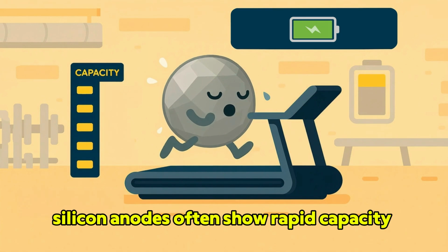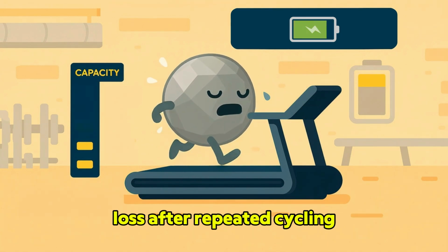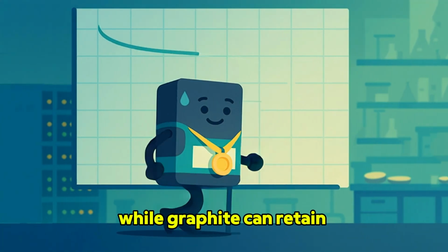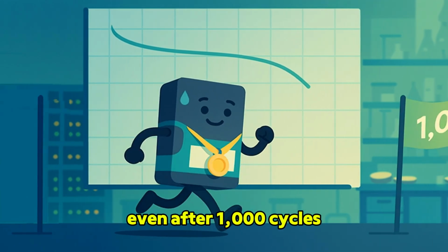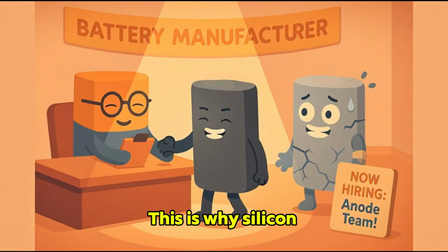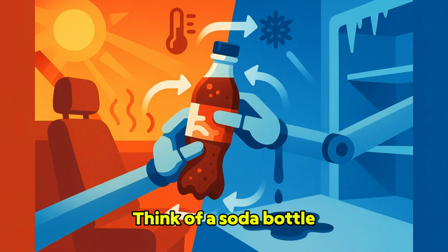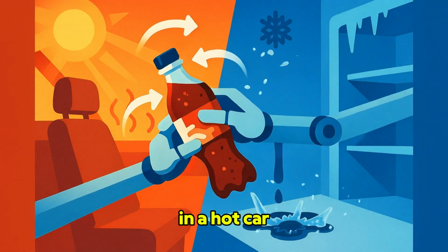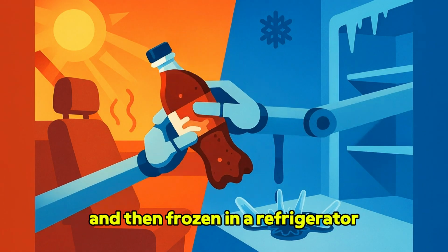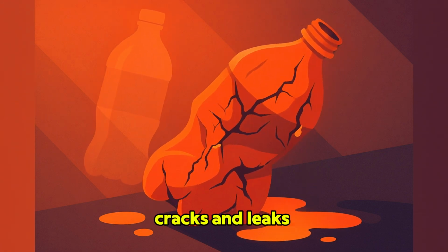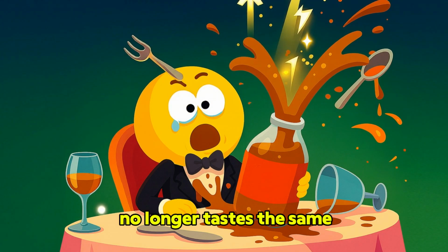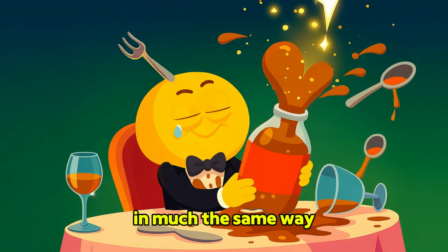In experiments, silicon anodes often show rapid capacity loss after repeated cycling, while graphite can retain more than 80% of its capacity even after 1,000 cycles. This is why silicon has not yet replaced graphite. Think of a soda bottle that is repeatedly heated in a hot car and then frozen in a refrigerator. It swells and shrinks until the bottle bends, cracks, and leaks, and the soda no longer tastes the same. Silicon expansion behaves in much the same way.